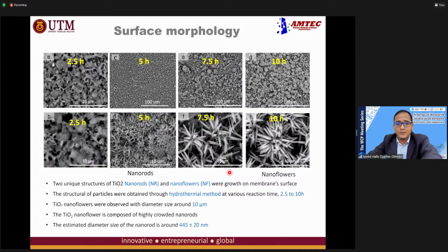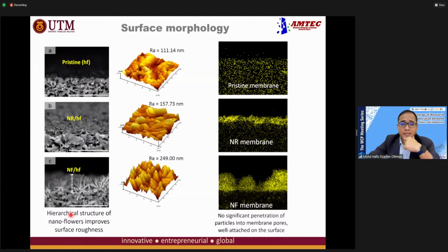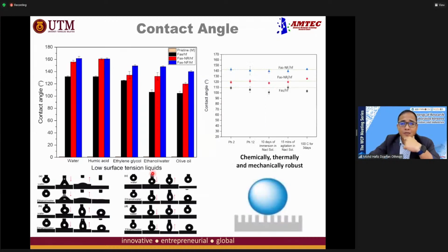We also measure contact angles with different types of liquid, like water and other low surface tension liquids. We can see that the result for the nanoflower has a higher contact angle than the nanorod and also the one without any coating. This means that by roughening the membrane, we can further increase the contact angle. It can not only repel the water, but also repel the organic pollutant in the water.